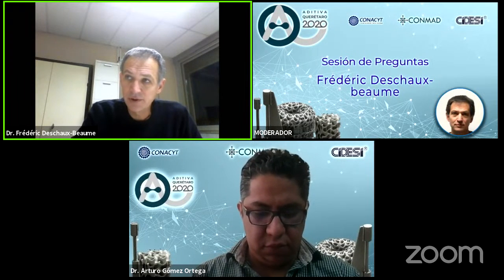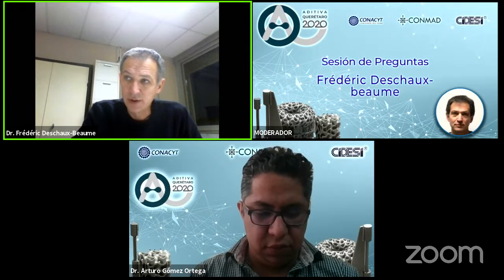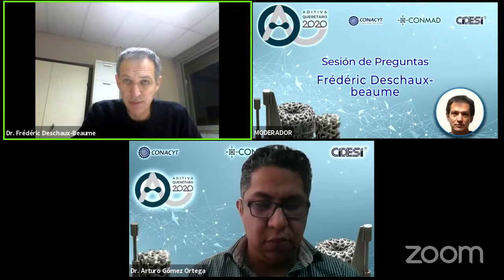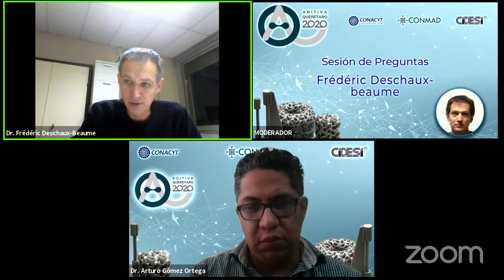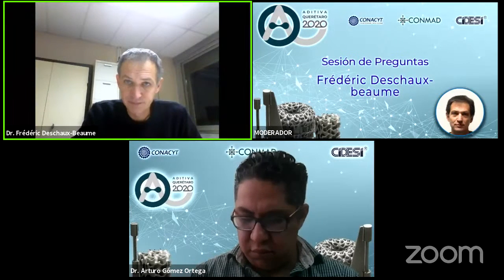We have no solution. The only solution is to create an inert atmosphere around the building piece. So we work on chambers around the manufactured samples to protect against the oxidation. But with titanium, it's a real issue, the content of residual oxygen.